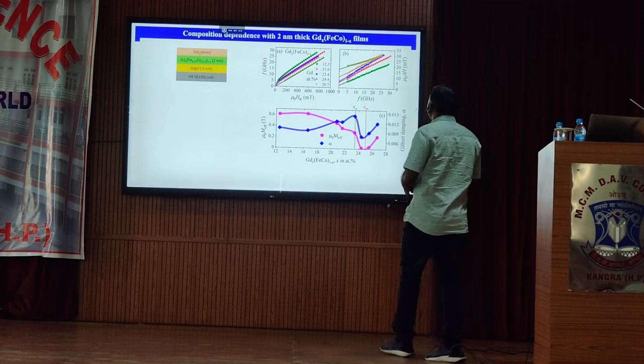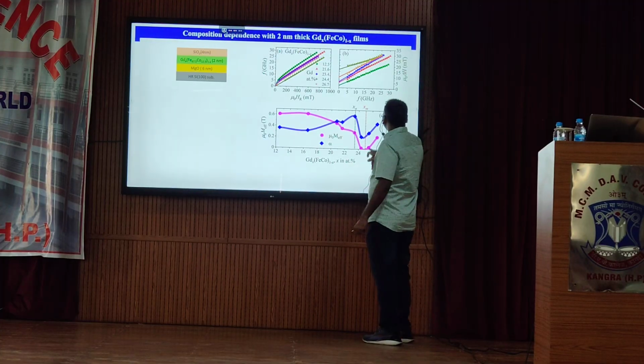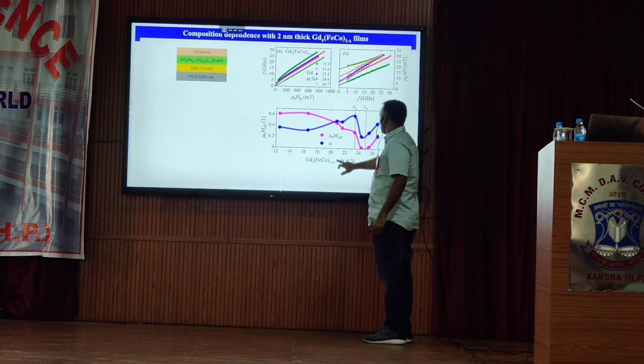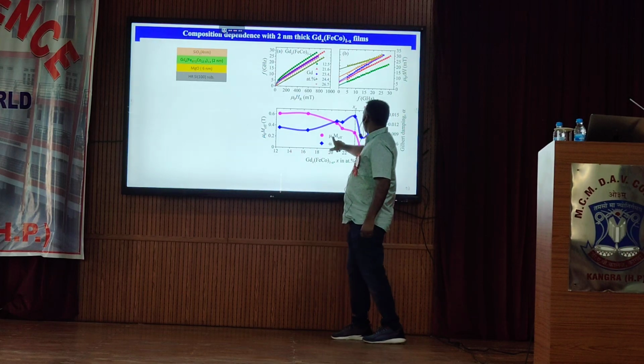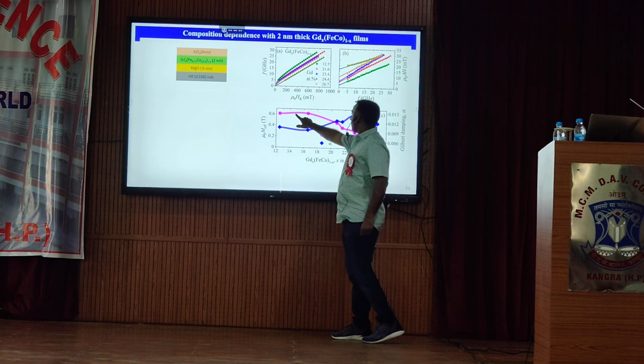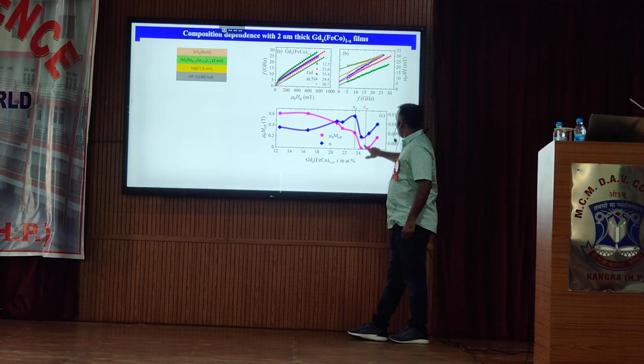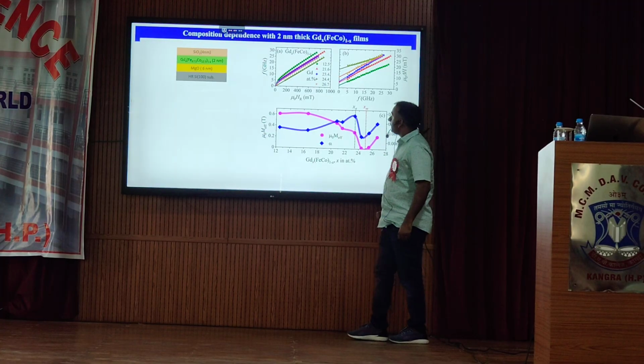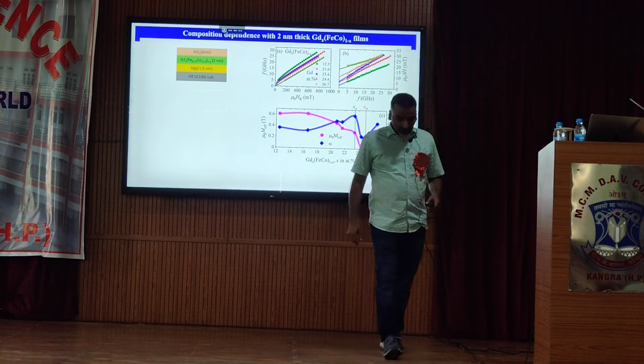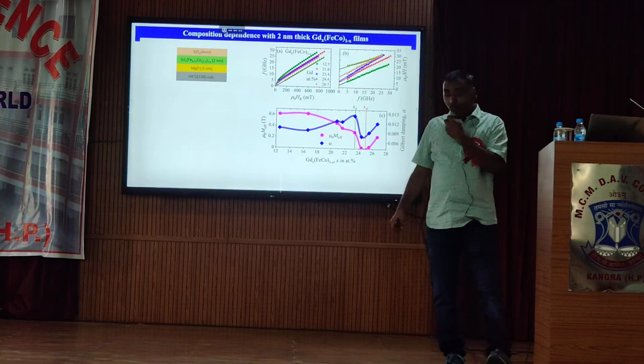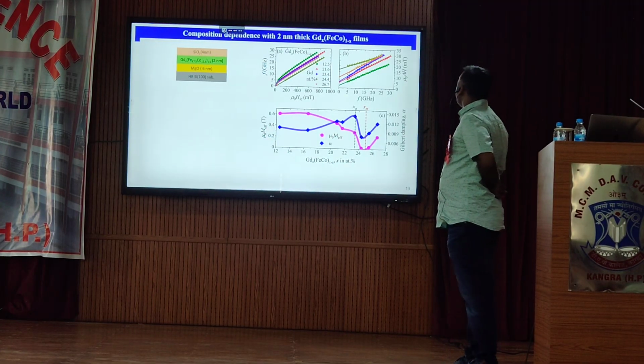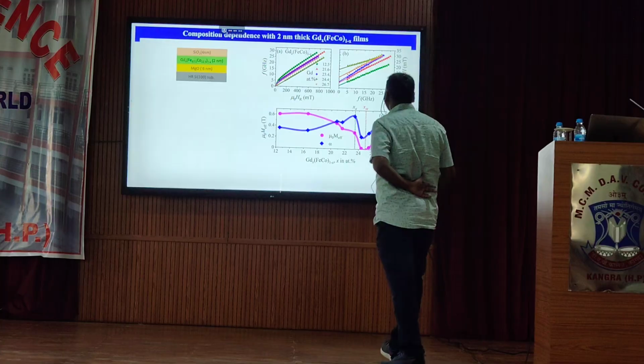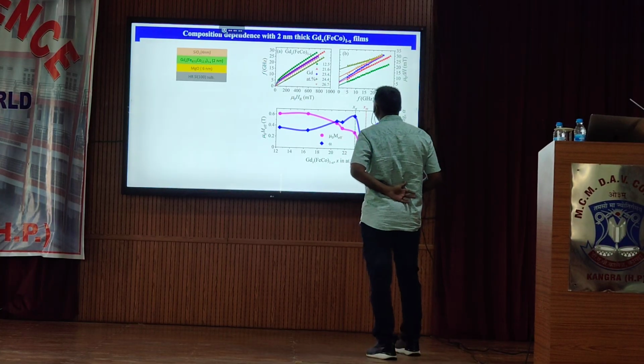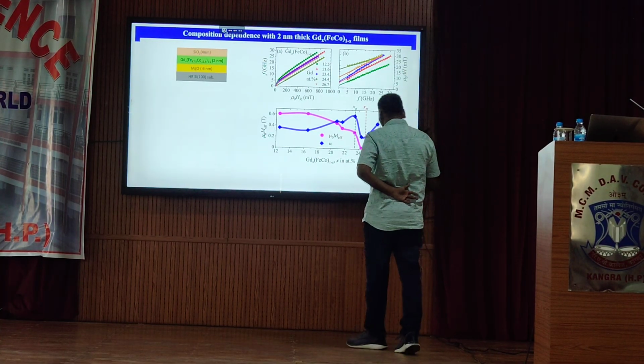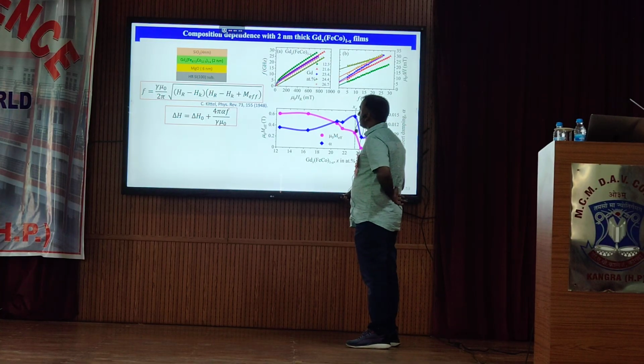So we obtain almost magnetization compensation near this 25% composition of gadolinium. As you can see here, the effective magnetization of the material is 0 at this point, and the magnetic damping constant is also minimum around this point. So with our ferromagnetic resonance measurement characterization, we confirm that we were able to get the composition near the angular compensation point, and that was very interesting if we are looking for a high frequency spin Hall nano oscillator using these devices.